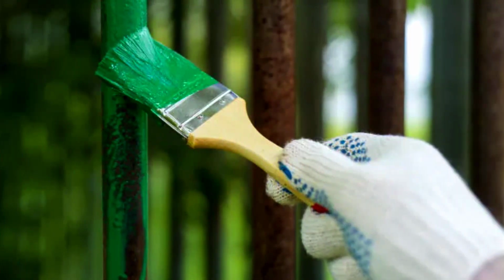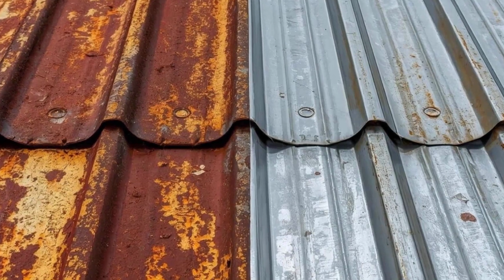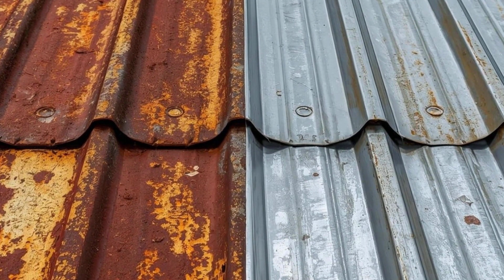Paint is not airtight, and it does not stop the reaction underneath it. The rust continues, and because it expands as it forms, it pushes the paint off from below in blisters. Meanwhile, you have sealed existing moisture in against the steel and made it impossible to see what is happening. A painted tool with rust under it is in worse condition than a bare, rusty one because it hides its own decline.